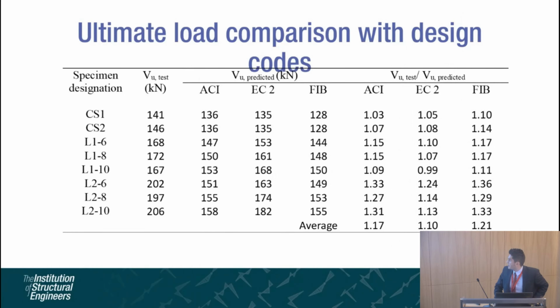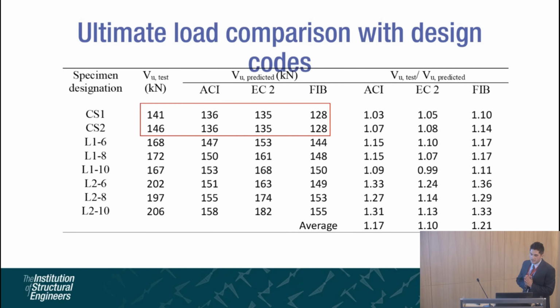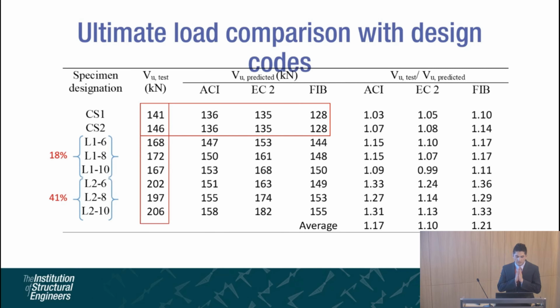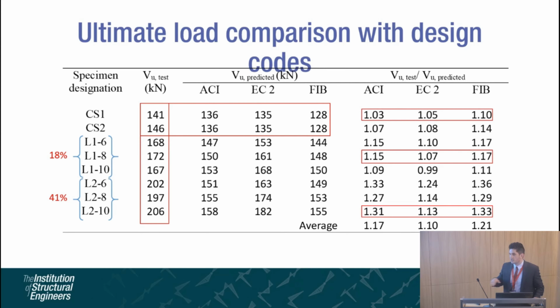As we can see in the ultimate load comparison, the design codes predict the ultimate capacity very accurately for the non-strengthened cases. These samples and strengthening layout number 1 both increase the ultimate load quite significantly. But when we make the comparison with the design codes, when we take the effect of the strengthening into consideration, it actually provides a rough guidance of what the failure load would be. So by using the modified method, we are actually predicting the maximum strength of the strengthened samples. And Eurocode 2 was the most efficient out of all of them. The reason is because it takes both the effect of effective depth and reinforcement ratio into consideration. The ACI and the fib Model Code do not take the amount of reinforcement into consideration. That's the reason their predictions are more conservative.